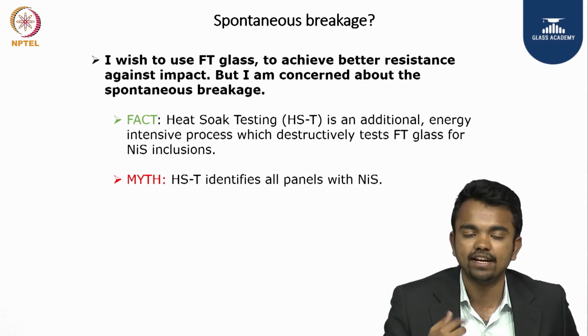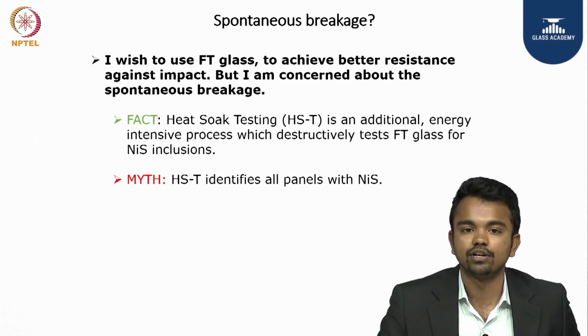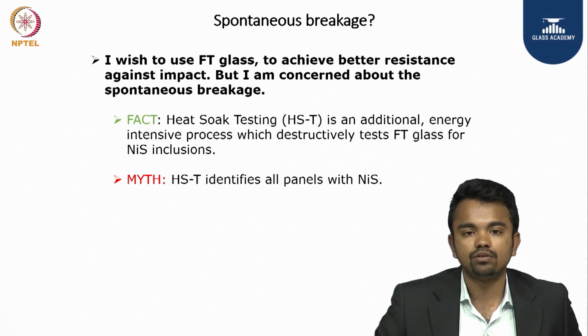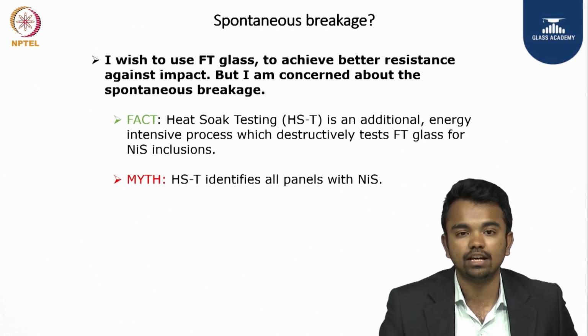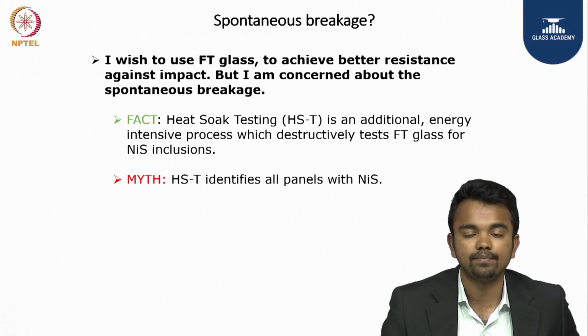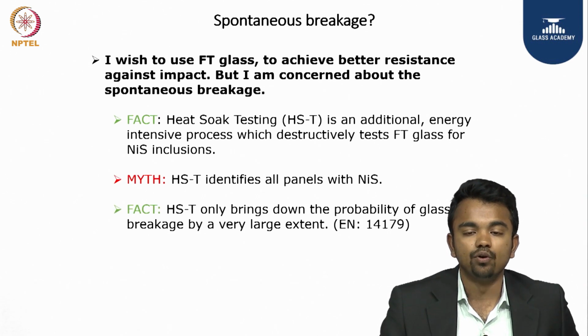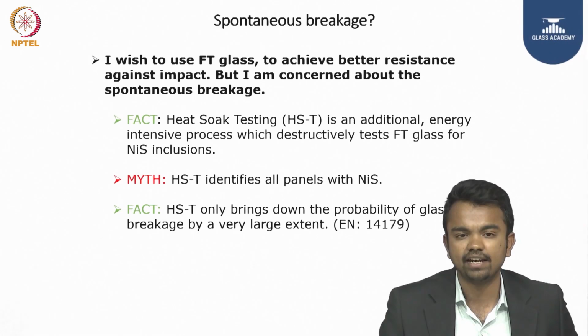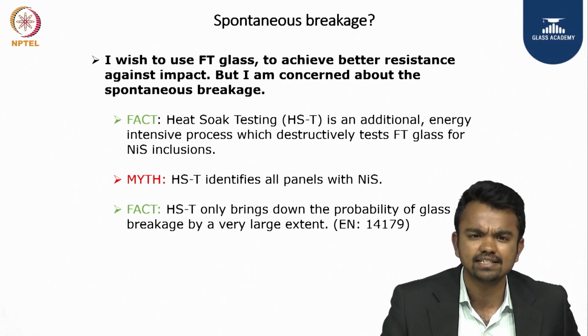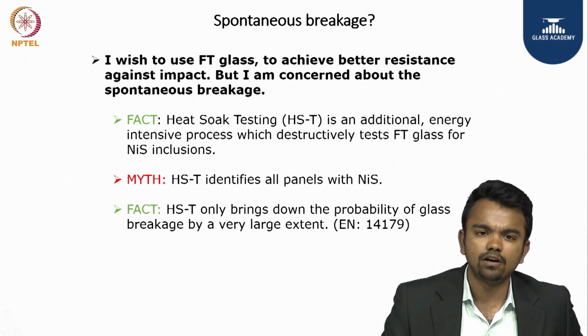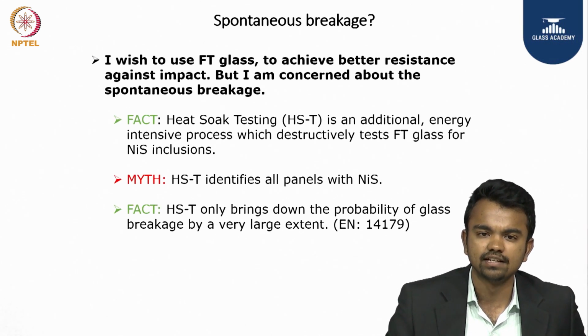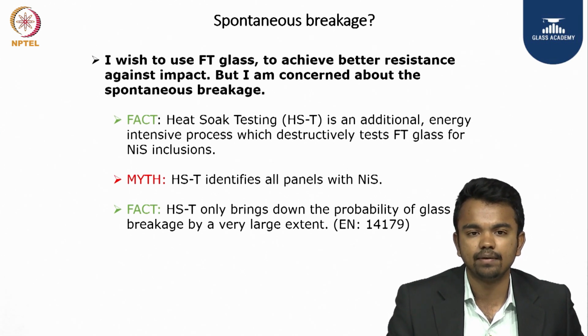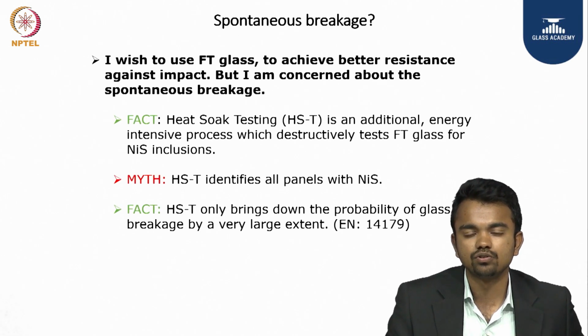So, even when I say that heat soak test is something which is going to benefit you to go with a fully toughened glass, it may not eliminate all the nickel sulfide included panels completely. So, it only brings down the probability of glass breakage. Of course, it is by a very large extent. The probability of glass breakage due to nickel sulfide after heat soaking reduces by more than 80% or close to 90%, but it is not nil.